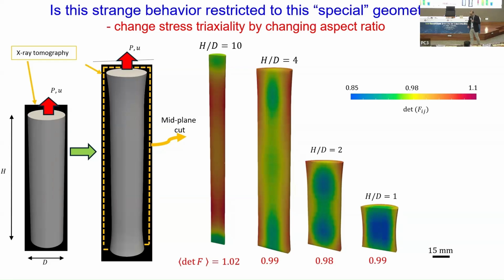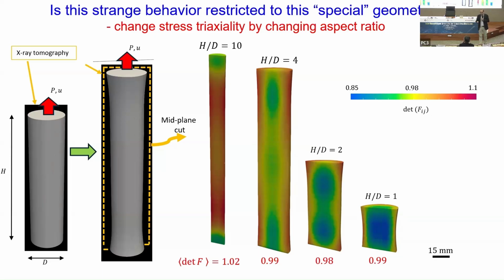Now, look at the length scale here. This is not some atomic length scale, right? This is 15 millimeters. So it seems as if at a very macro level, this specimen sees the boundaries, these glued boundaries that we had of the platens. Somehow or other, this material is actually able to see these boundaries, i.e. the gradients that are being created because of these boundaries. Okay, now if you agree that all these problems are occurring because of some boundary gradient effect, that the gradients of strain that are being created, then